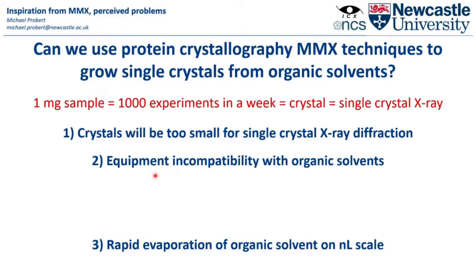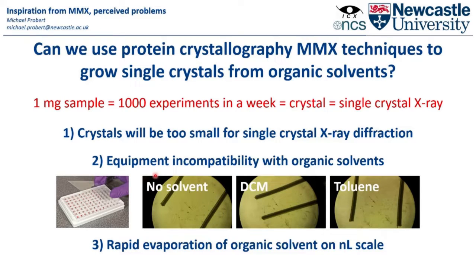Even so, there was a little bit of worry over the materials and our organic solvents. Plastics generally don't survive well with aggressive organic solvents. So in collaboration with Paul Thor, we set up some tests. We took some of the dispensing tips and left them submerged in our solvents for a period of time. Turned out to be quite a lengthy period of time, and then had a control to compare against. And essentially we saw no degradation of the plastic over several days.